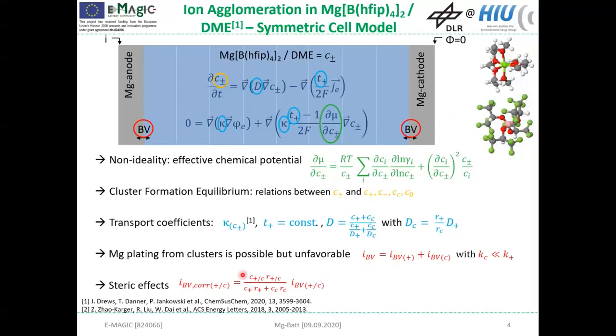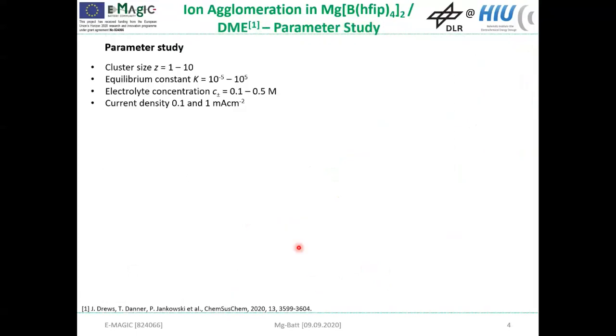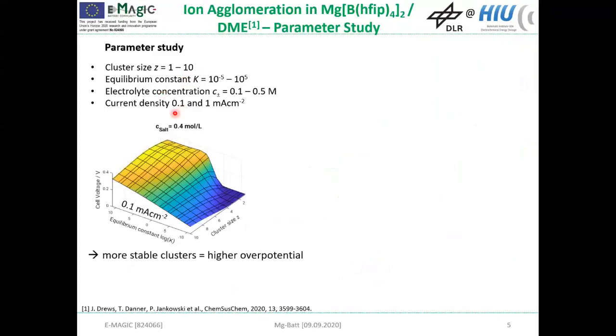So with this model, we have now done a parameter study and looked at different values for Z and K, as well as the electrolyte concentration and the current density. So here you can see the results for 0.4 molar electrolyte at the lower current density, and we found that more stable clusters lead to a higher overpotential. And this expected behavior is more pronounced for smaller clusters.